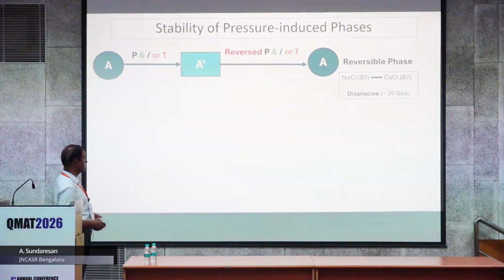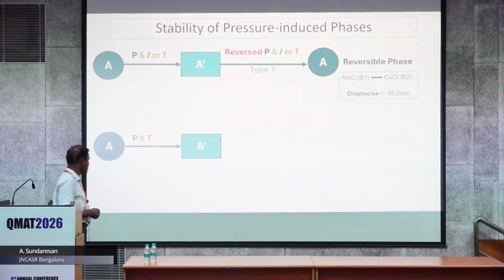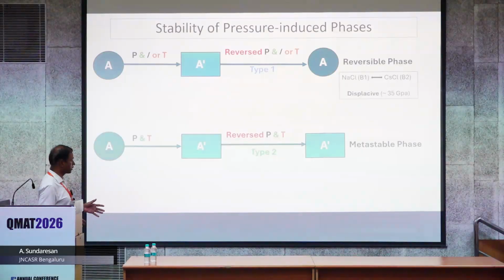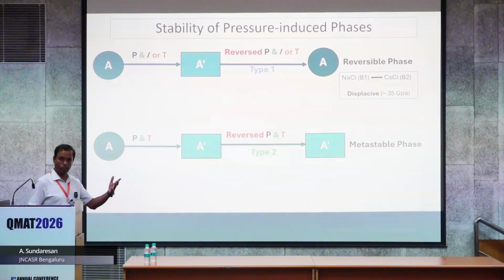So it will come back to this. The other type is: you start with your material, apply pressure and temperature, and you stabilize another phase. There is a phase transformation, and when you reverse pressure and temperature - of course when I say that, we have to quench it, because to stabilize this metastable phase, you retain this metastable phase, like diamond or any other phase transformation. You can stabilize it, unlike this phase.